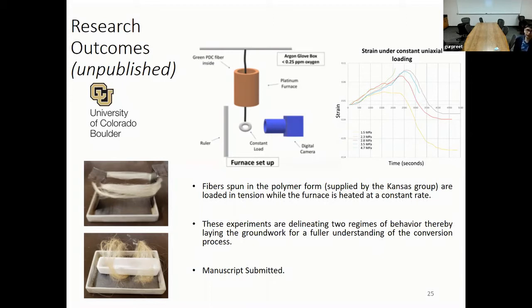So this, we believe, is delineating two regimes. One is the polymer regime. These were as-spun fibers. So we believe that as the sample is heated to elevated temperatures, it's still in the polymer form, so it tries to expand in the beginning, and then it switches, and once it's ceramic, it actually shrinks. So it's an interesting observation, and we believe that's laying groundwork for a fuller understanding of the polymer to ceramic conversion processes. And the group at University of Colorado has a manuscript submitted.